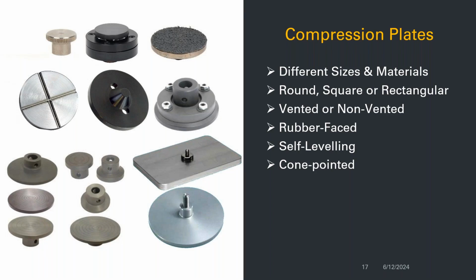And these can also be vented or non-vented. Vented compression plates are usually used on empty containers, in order not to build up pressure and spike your compressive force values. We use the vented compression plate to essentially let out the air, so you can focus on the actual structural integrity of the samples you're testing. And then we use the non-vented compression platens on samples that are pretty much ready for market, filled and capped containers, which is more of a real-life test application, especially to determine whether they'll survive however many cases are stacked in transporting from the production floor to the store, and so on. And then there are also rubber-faced compression platens that prevent any slippage on the surfaces of samples that are unusually smooth.